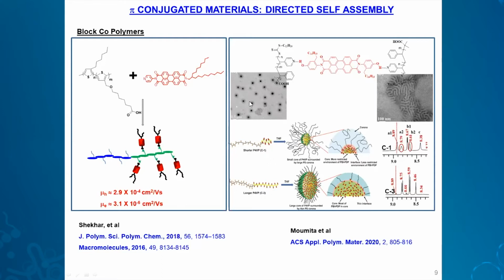Suppose we vary the chain length of the starting block, this is polystyrene and this is P4VP. If we increase the block length and then do the self-assembly with the small molecule, these types of morphologies are obtained: the core-shell type structure with a long hairy structure or a short hairy structure, which we can trace with NMR as new peaks coming up. This was a beautiful study in which we could demonstrate for the first time that this is retained in solution also. So these are some of the concepts that we did with pi-conjugated materials for photovoltaic applications.